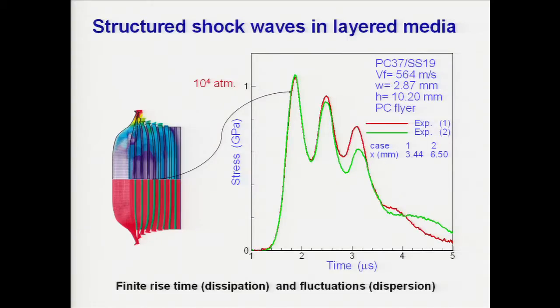And in this case, we measure the stresses within the layers. So here, the stress is measured inside the layer during an impact. The impact is happening at about 500 meters per second. So this is the stress. Here, you can see there's a long, finite rise time associated with the shock. And also, the shock is not flat anymore at the top, the Hugoniot state, but it's oscillating. These oscillations are due to the fact that the shock waves are reverberating back and forth within this media.